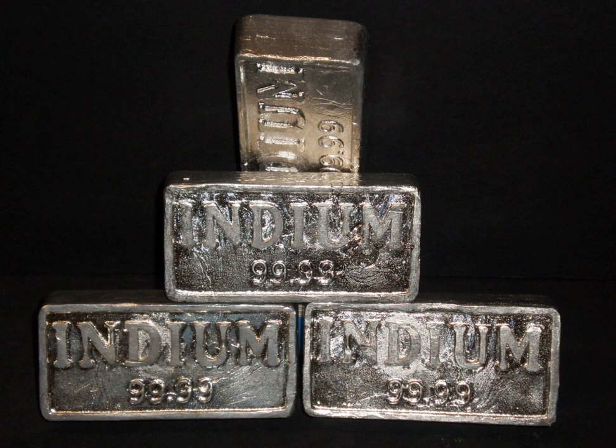Indium displays a ductile viscoplastic response, found to be size-independent in tension and compression. However, it does have a size effect in bending and indentation, associated to a length scale of order 50 to 100 micrometers, significantly large when compared with other metals.